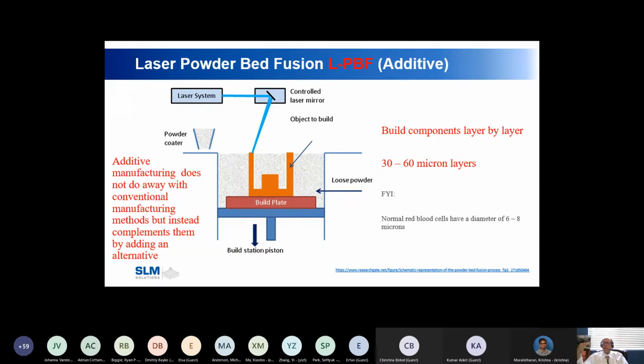And some parts have thousands of layers added to them. And when we say a layer, we're talking about 30 microns, and that will melt down to a thickness of about 10 microns. So you just constantly are rebuilding, relayering this part until you get it built.